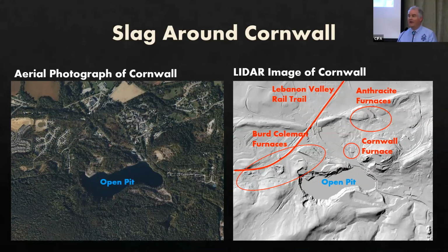The simple answer to that question is because you see it flow out of the furnace. You can see the difference between the slag, which is first tapped, and then the iron, which comes along behind. So typically, if they were tapping the furnace to remove the slag and they started seeing liquid iron come out of that port, they would stop it and then they would start tapping the iron out of the furnace.